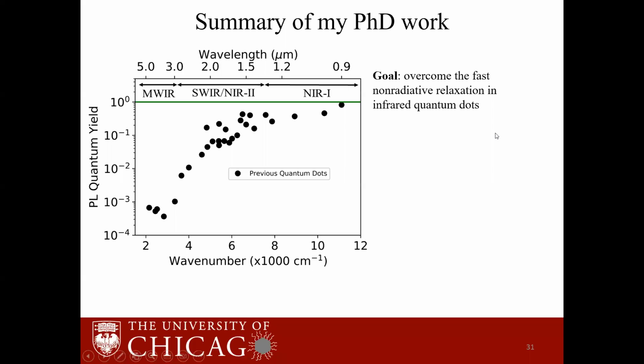So I want to end by summarizing what I have discussed till now. We started by this trend of decreasing quantum yield as we go to longer wavelengths. And the fact that mid-infrared quantum dots have a lot of potential for thermal imaging, but their quantum yield is extremely low right now. So in order to determine the relaxation mechanism and slow the rate, we have calculated the rate of FRET between the quantum dot and ligand molecules, as well as the quantum dot to solvent molecules.